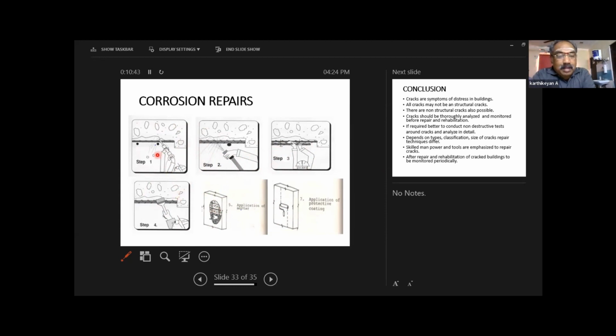So remove the cover concrete, remove the corrosion. If there is a loss of more than 20%, you have to add further reinforcement. Apply corrosion resistant paint and apply a bonding coat. Provide additional screed concrete or micro concrete and then a mortar finish. This is how, step by step, you have to make corrosion repairs.